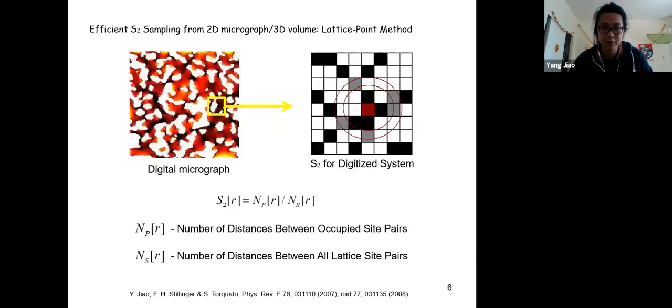And based on this definition, you can clearly see that we can reduce the microstructure. We can actually convert this digital volume to a set of functions, right? You can compute 1 point, 2 points, 3 points. In principle, you can continue this series to whatever you think is sufficient to quantify the microstructure. But this provides a hierarchical way of reducing the dimensionality of that whole microstructure space to a set of well-defined mathematical functions, right?